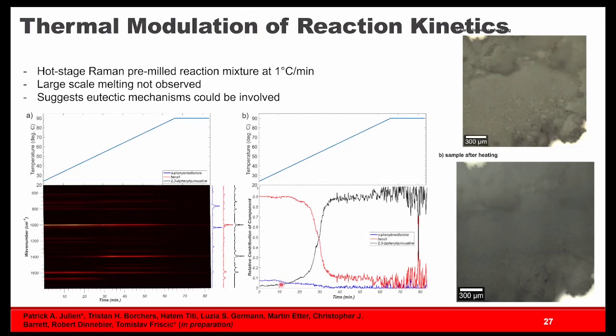And what we saw, which was quite interesting, is if you line up here, you start to see, again, sigmoidal reaction kinetics. So again, we just heat it, and we're constantly taking Raman spectra every 10 seconds or so. What this suggests is that it's probably thermal that's driving this type of sigmoidal behavior in the case of the high annealing frequencies.